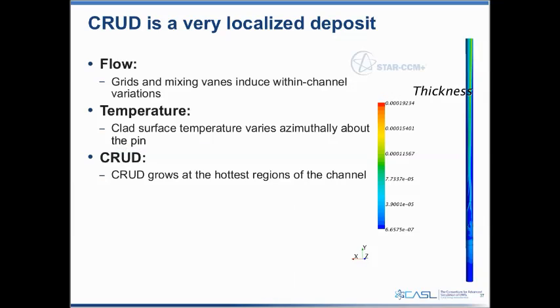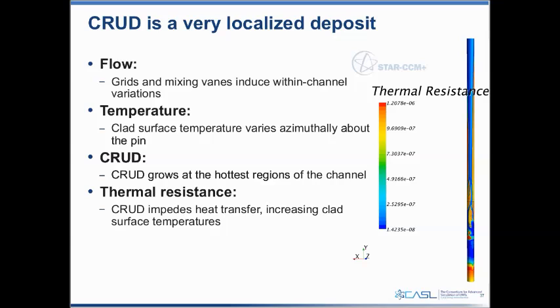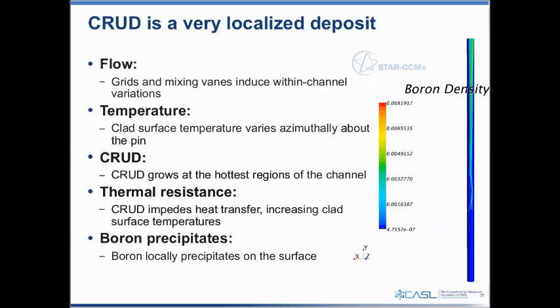Due to that azimuthal temperature variation, you have crud growing in the hottest regions of that channel, building up and getting thicker. That crud impedes heat transfer, which increases the clad surface temperatures and affects the temperature in your fuel. And as mentioned earlier, as that builds up, you get more and more boron that starts to deposit on the fuel, on the surface of the cladding in those crud regions.